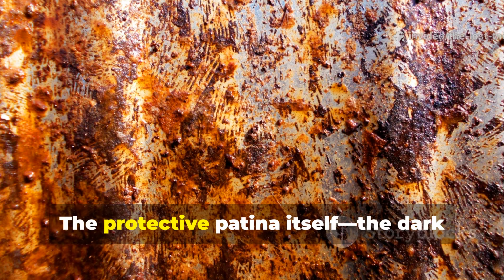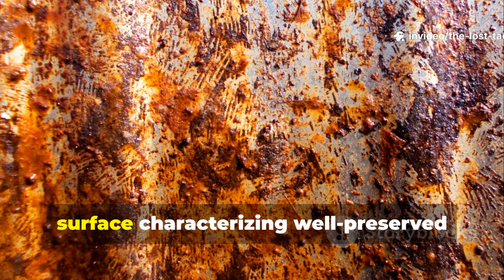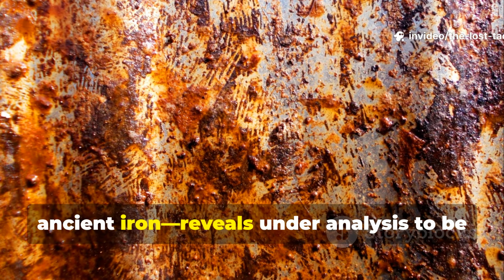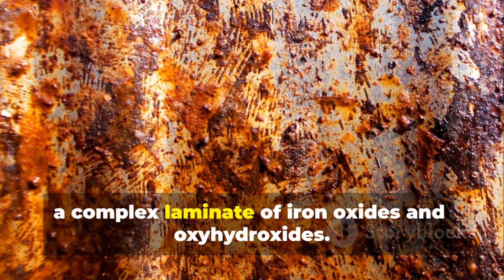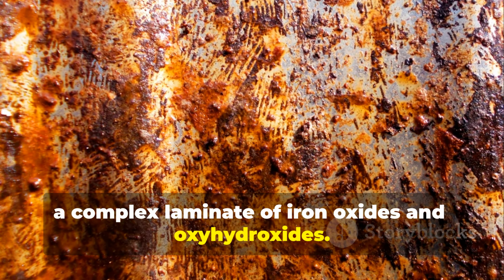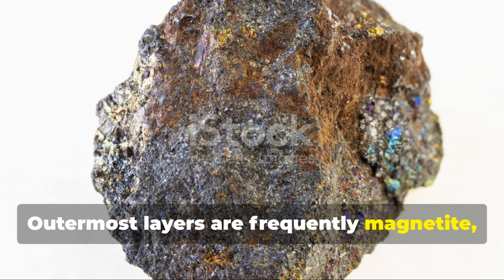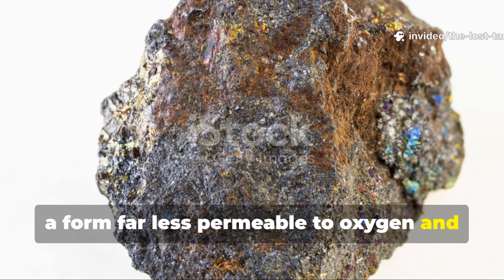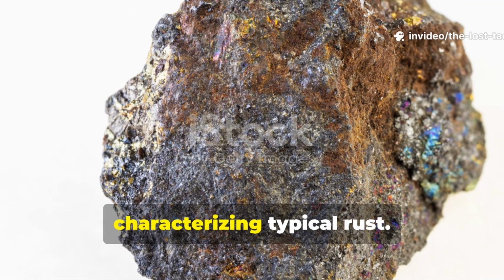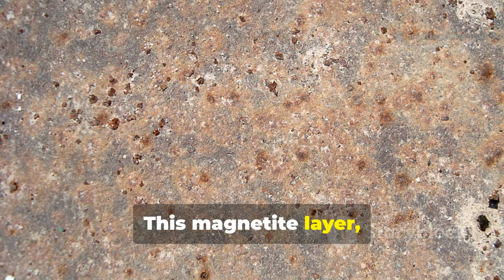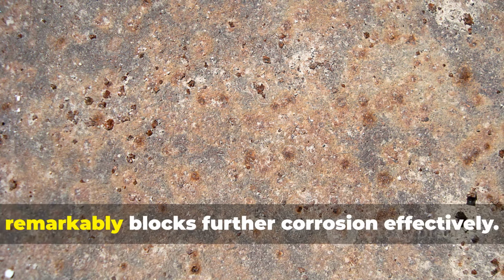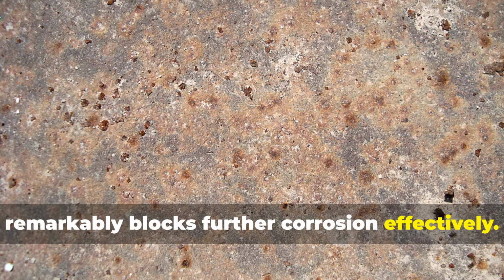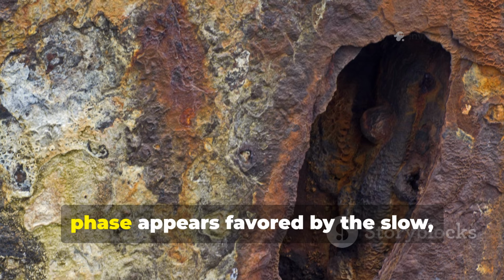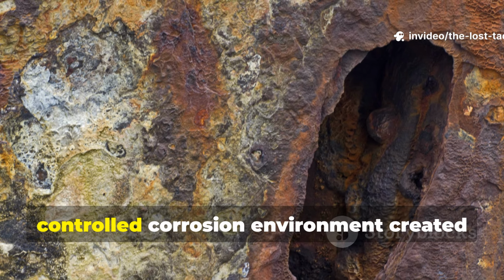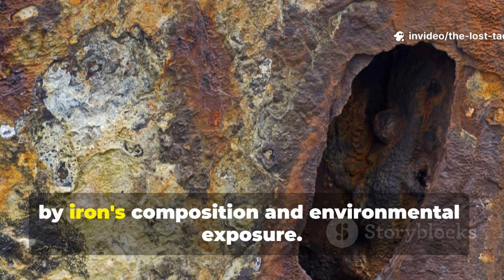The protective patina itself, the dark surface characterizing well-preserved ancient iron, reveals under analysis to be a complex laminate of iron oxides and oxyhydroxides. The outermost layers are frequently magnetite, a form far less permeable to oxygen and moisture than reddish ferric oxides, characterizing typical rust. This magnetite layer, sometimes just micrometers thick, remarkably blocks further corrosion effectively. The formation of this specific oxide phase appears favored by the slow, controlled corrosion environment created by iron's composition and environmental exposure.